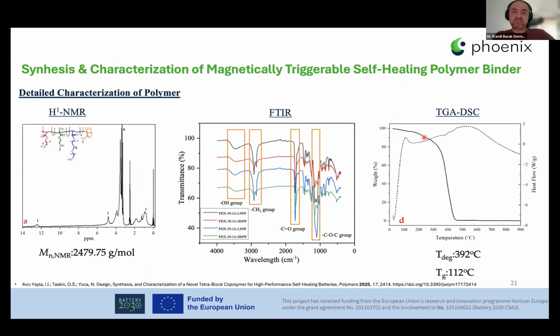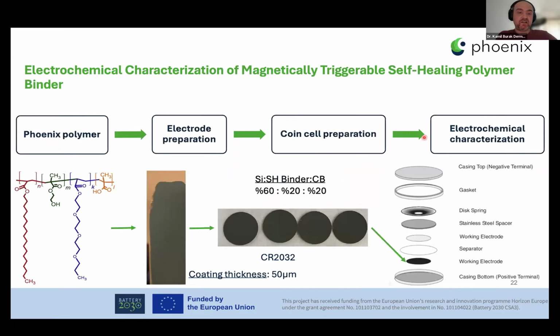And then the synthesis and the characterization of the magnetically triggerable self-healing polymer binders. That is also one part of the project. Here we synthesized magnetically triggerable self-healing polymer binders. And for these binders, the characterization has been done by using NMR, FTIR, and TGA analysis. And afterwards, we prepared a cell out of them, at coin cell level, using 60% silicon, 20% self-healable binder, 20% carbon black.